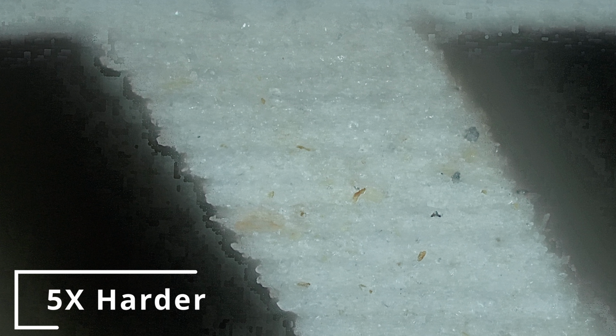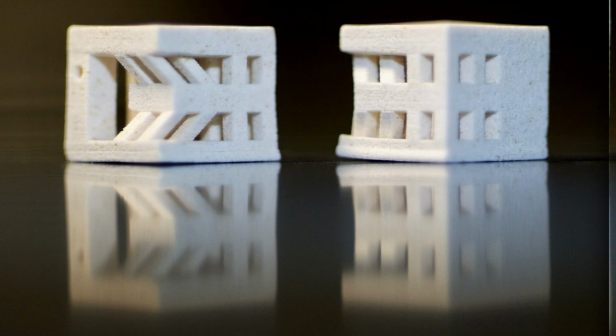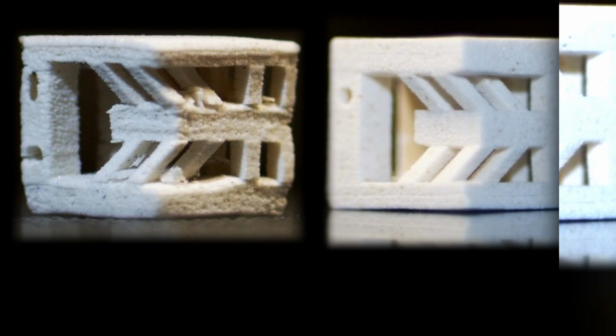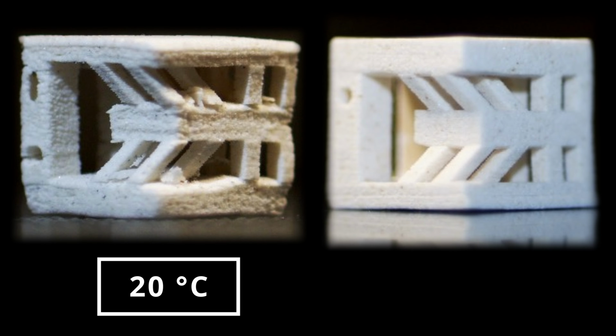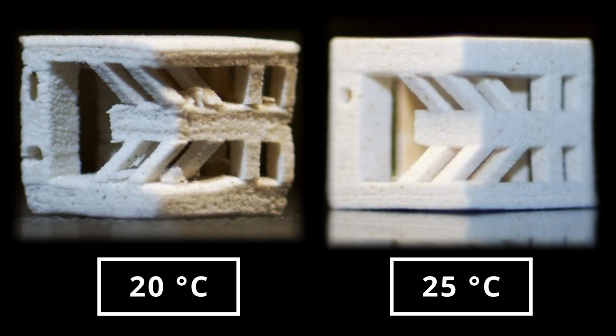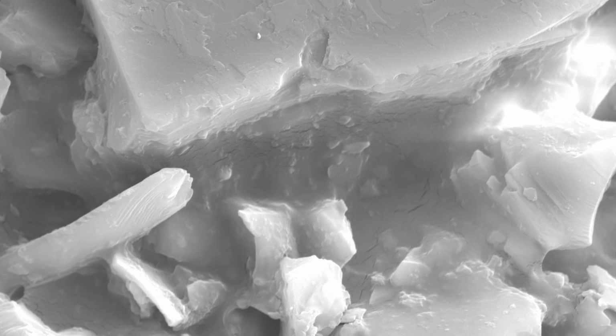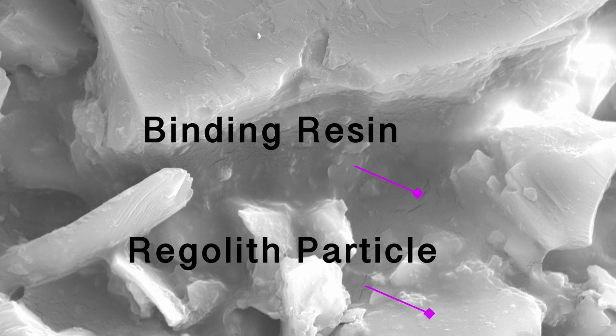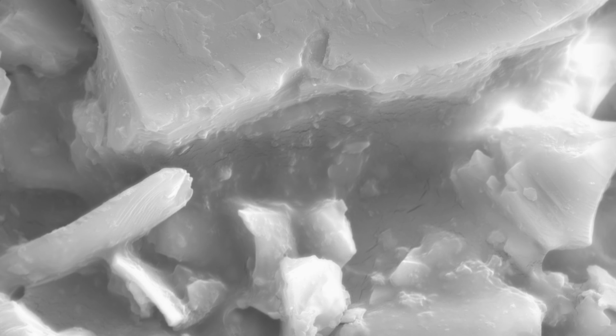The final sintered piece is 5 times harder than mild steel, and it goes back to the color of the regolith because all the resin has been removed. The piece on the left was printed at 20 degrees Celsius and sintered, and the piece on the right was printed at 25 degrees Celsius and also sintered. This is an animation created using actual scanning electron microscope images. You can see that the resin is vaporized and the particles fuse together.